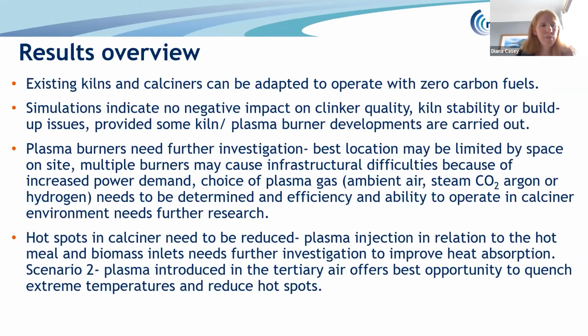So just in terms of a bit of an overview of what those results were showing, we found that existing kilns and calciners can be adapted to operate with zero carbon fuels. The modelling indicates that there's no negative impact on the clinker quality, the kiln stability, or any sort of build-up issues within the kilns. However, some kiln and plasma burner developments are needed to refine things slightly, just to make sure we don't unnecessarily wear out refractories and things like that.